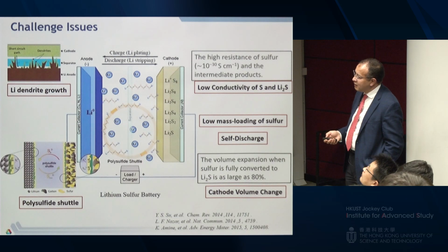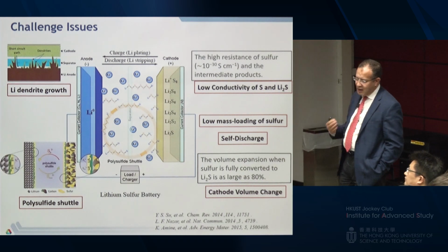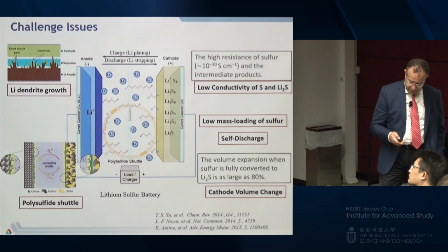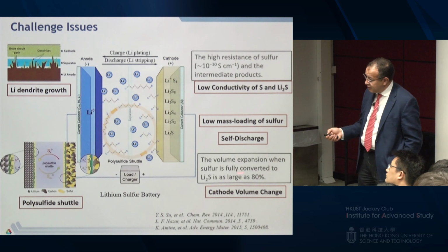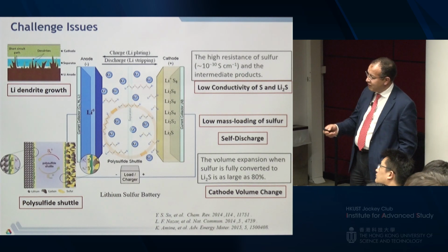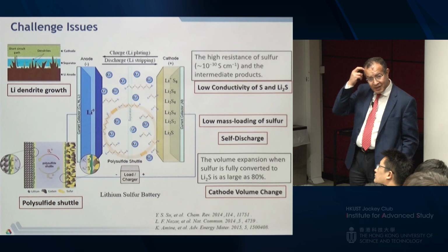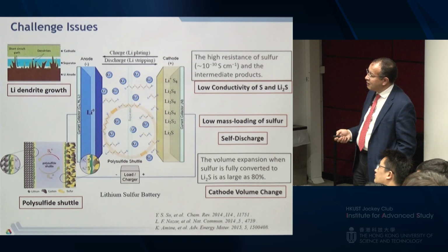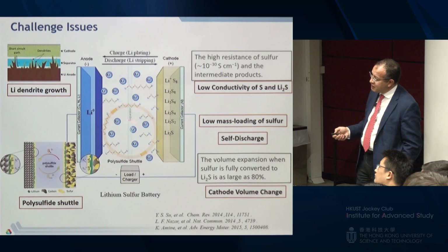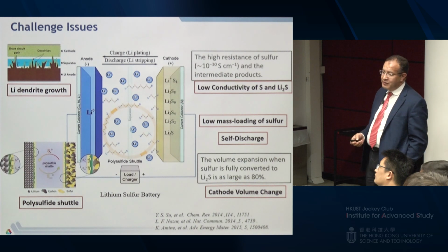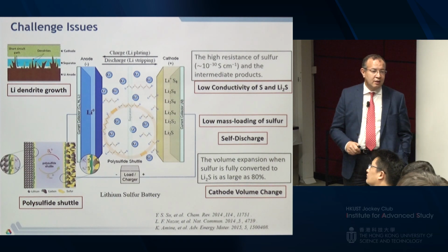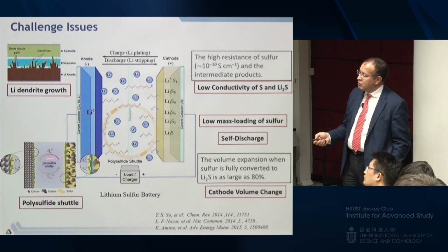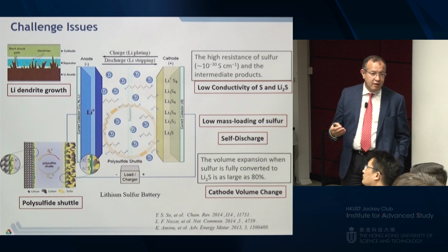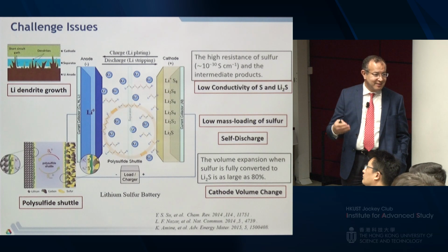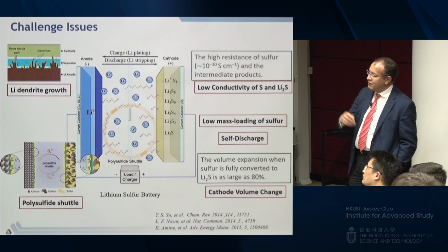So that's not good. The other thing is you have to figure out a way to put high loading. That's one of the problems with sulfur. And then there is an expansion of volume when you move from sulfur to Li2S, for instance, almost 80%. You have to take care of that as well. And then you have the polysulfide that dissolves, and then they tend to shuttle to the anode and stay there. And that's loss of active material. You're losing sulfur.